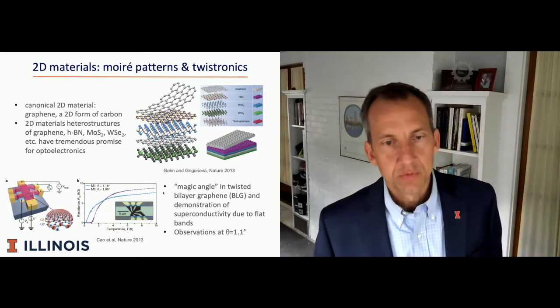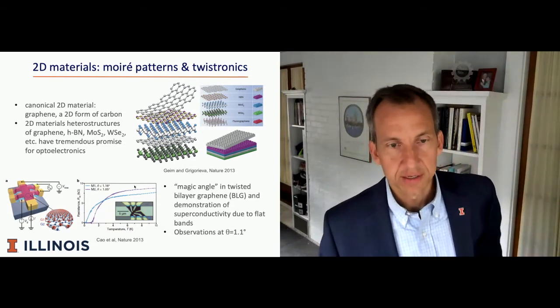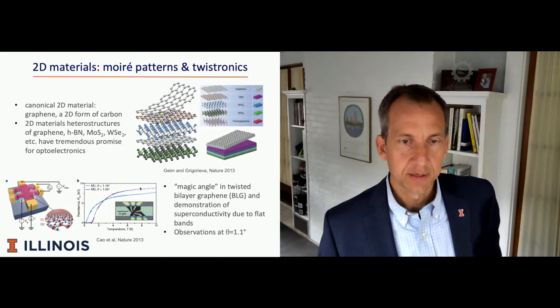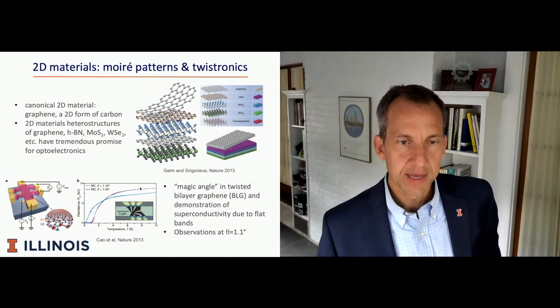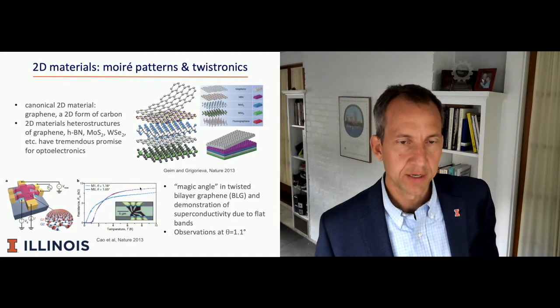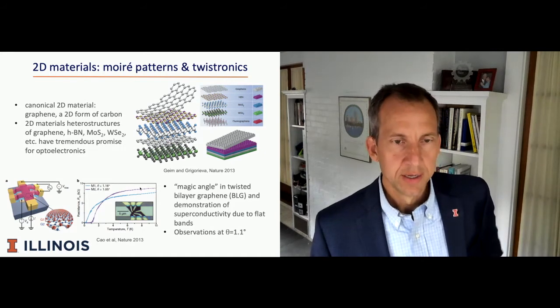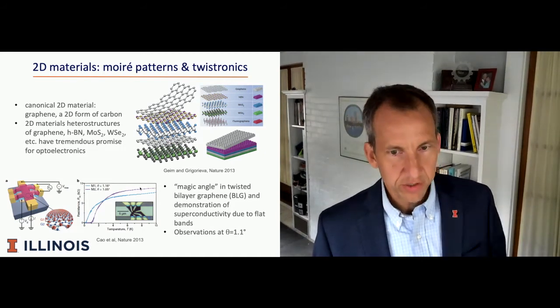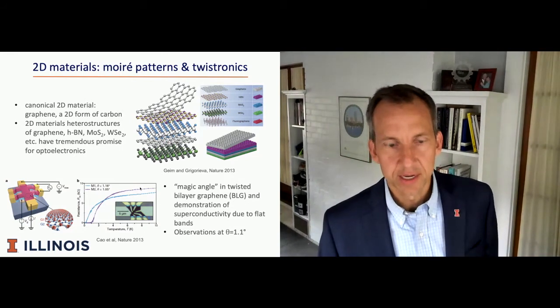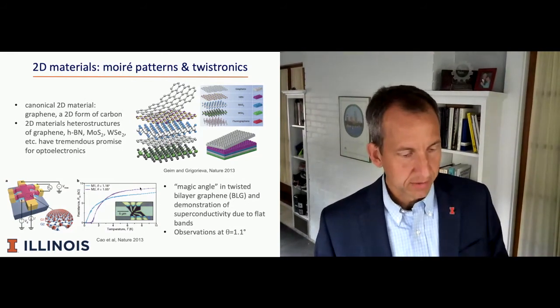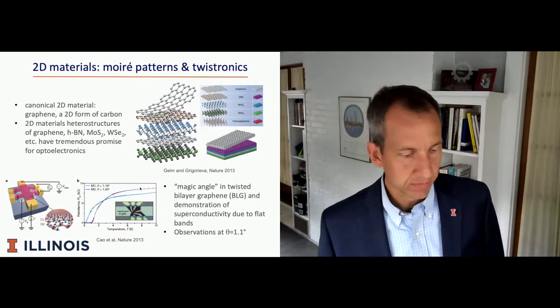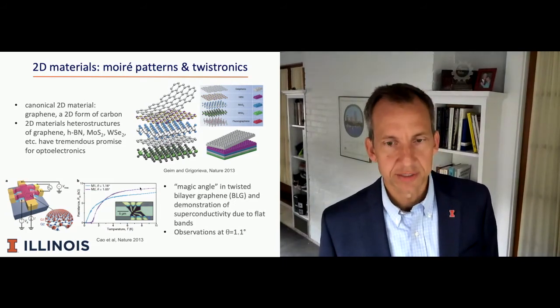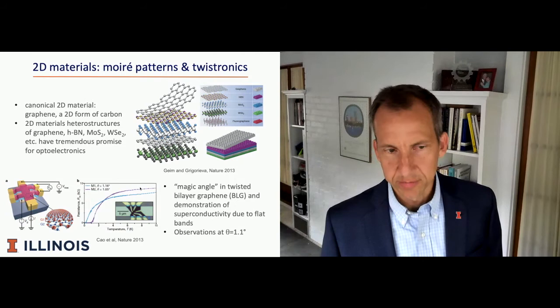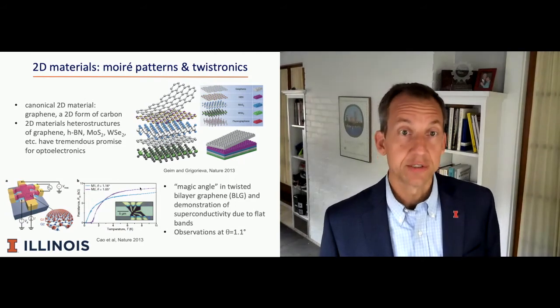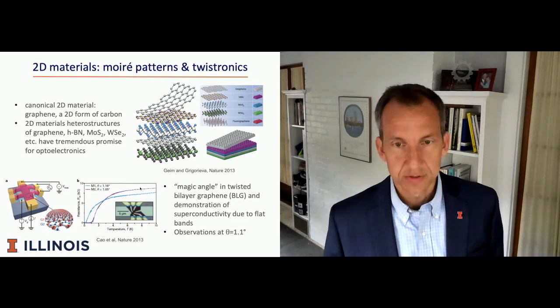Now, one would like to be able to understand why that is, and the work on the mechanics and the electronic structure of this phenomenon, these are ongoing. But in the electronic structure, we do know that there's a particular band alignment that happens at 1.05. This is where we observe so-called flat bands. So this is a little bit of motivation. There are other interesting properties that occur in these twisted bilayer structures, and this area is referred to as twistronics.